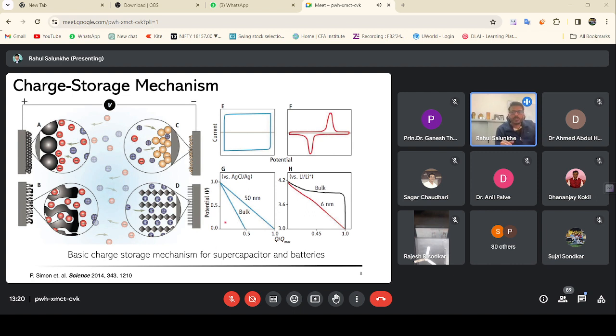Also, if we see the galvanostatic discharge profile, we will observe that for EDLC material, discharge is linear both in the bulk and in the thin film form, but a plateau in voltage is observed for the bulk battery material. That is, it sustains a linear voltage up to a certain time. So this is about the charge discharge mechanism.